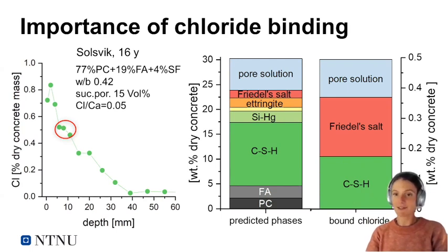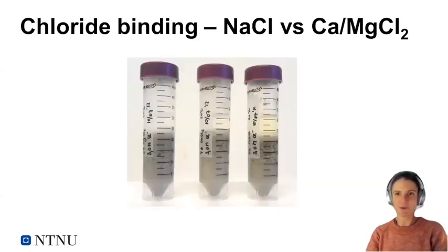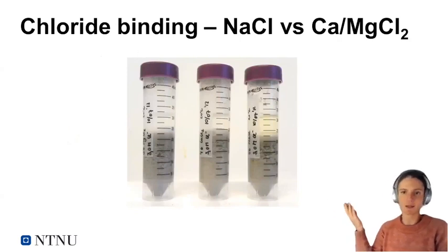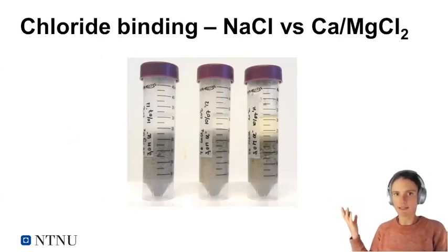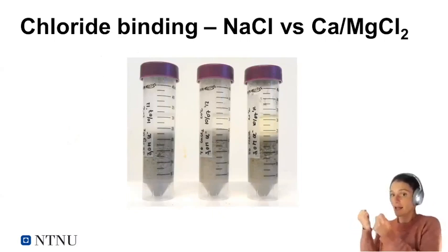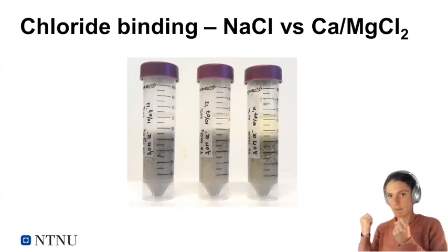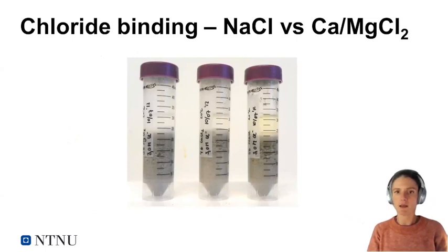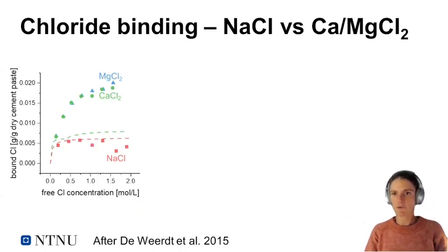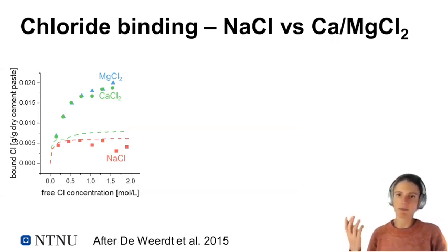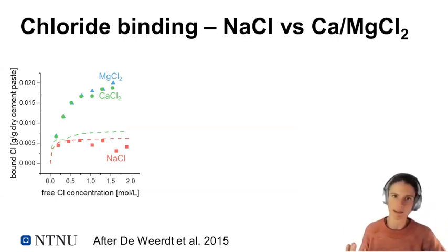So that's why during my postdoc, I started playing around with chloride binding. And I used this setup where I put well-hydrated cement paste in contact with different chloride-containing solutions and checked how much chloride they can actually take up, and also tried to analyze the solids to see what phases actually form. So the first and very simple setup I did was looking at the cation effect. So comparing chloride binding when exposed to sodium chloride with chloride binding when exposed to calcium or magnesium chloride.